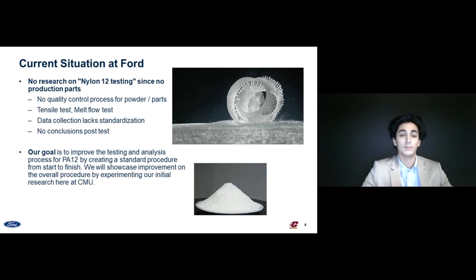We saw what materials were being used, how it was being tested, and we saw that the procedure was not efficient at all. We saw that there was no quality control processes for the powder or the parts. They were conducting a tensile and a melt flow test. However, there was no significant data collected from these tests, and they lacked standardization. And really, there were no conclusions being drawn from these tests.